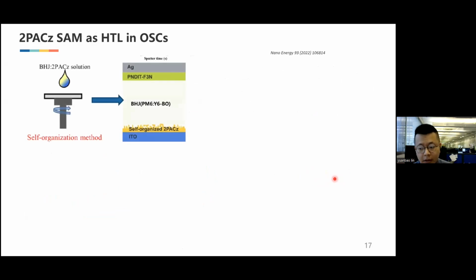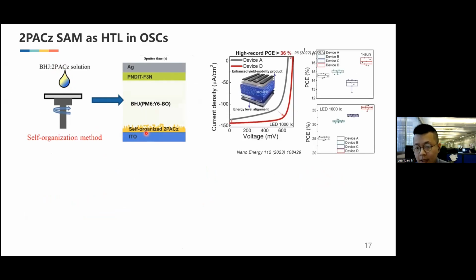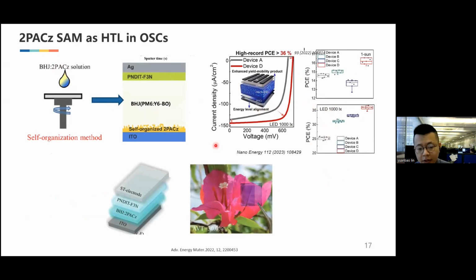Also, lots and lots of people use these 2PACz now. For example, they can put the 2PACz in the bulk heterojunction solution, and after spin coating, this 2PACz can self-organize onto the ITO surface. They can also combine the ITO 2PACz and the bulk heterojunction 2PACz in indoor solar cells, and they can get a very high PCE. Also, because this 2PACz is very thin, this system is more suitable for transparent OPV devices.